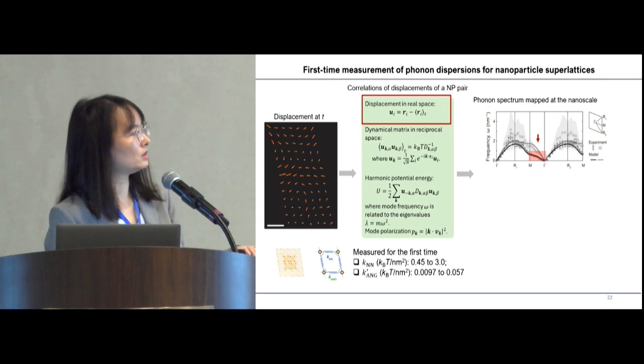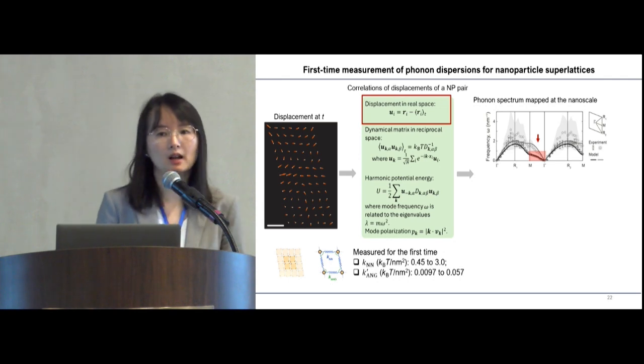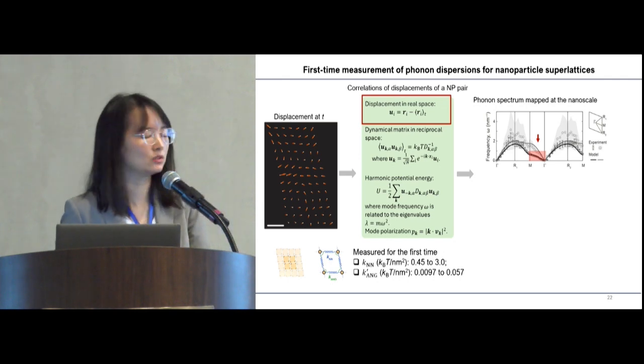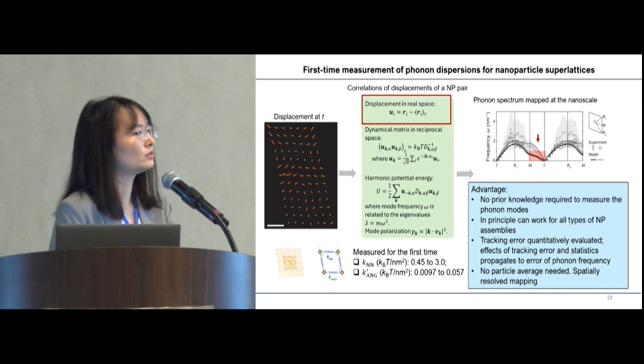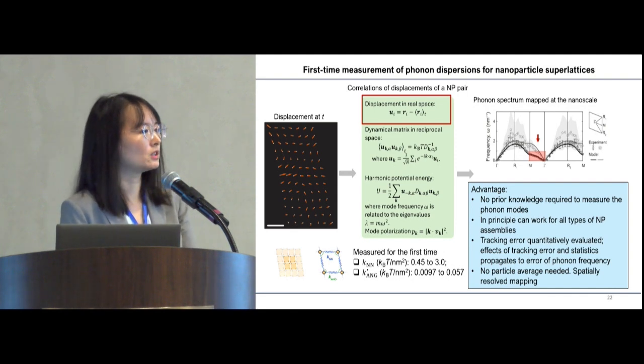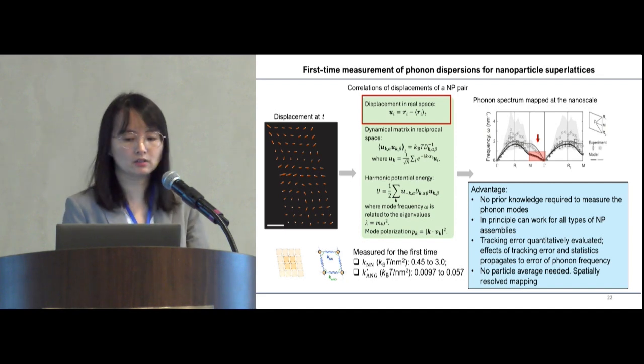We're also able to develop a bead-spring model for our complicated nanoparticle system, which matches really well with our measurement, which can allow us to measure the spring constant for the first time at the nanoscale. This method does not require any information about the particle size, shape, and interaction. We can do error propagation to make our measurement really accurate.